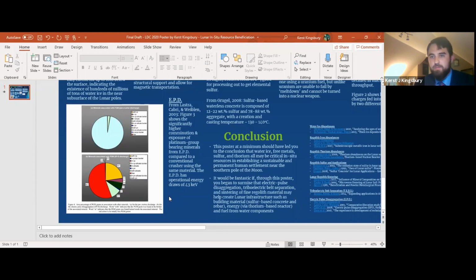But by mining only the surface components of the regolith, and then being able to break those regolith particles down to very small sizes, we might be able to better partition out elements of the regolith while potentially not being high energy. I believe that this has a benefit. This process may be potentially better than a process that melts the water ice out of the regolith, because with any type of heating element, you may lose a considerable amount of the water to sublimation, whereas this process could operate for the ice and the regolith at similar temperatures. And for the extraction technique, you wouldn't necessarily even have to differentiate between both of those resources. The EBS would hypothetically separate both very effectively.